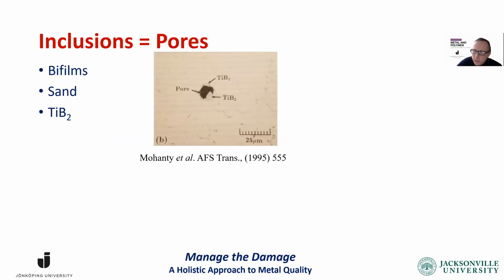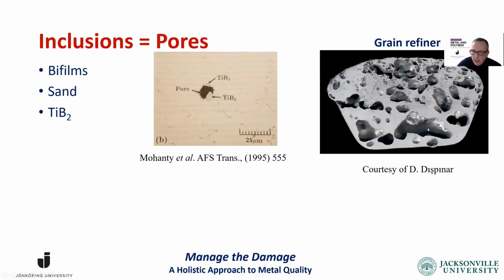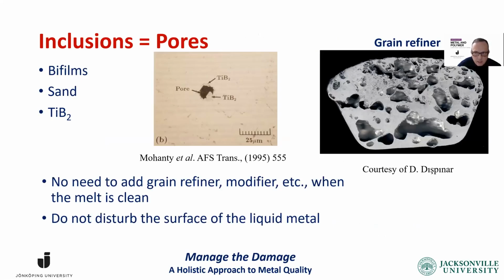When we produce inclusions, we produce bifilms like sand, or even when we add grain refiner. All that grain refiner does is distribute porosity. Here's an RPT of a grain refiner, courtesy of Derya Dushplar, and what it does is just create pores. So the real purpose of grain refiners is porosity management. There's no need to add grain refiner or modifier when the melt is clean. That's what they practice in aerospace castings. You don't need it. Just do not disturb the surface of the liquid metal.